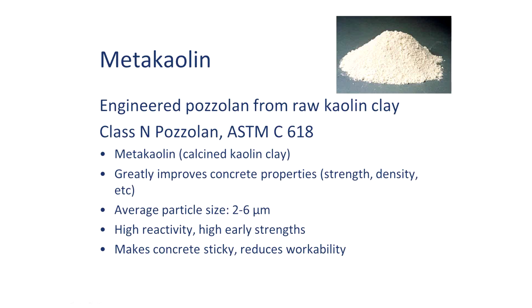It gives you a very highly reactive, very small particle pozzolan that can actually give you higher early strengths. You can get higher 3-day strengths using metakaolin than you would if you didn't use pozzolans at all. So this is one of the few pozzolans that actually boosts your early strength.